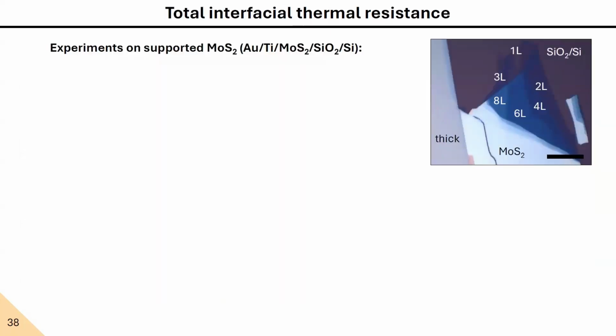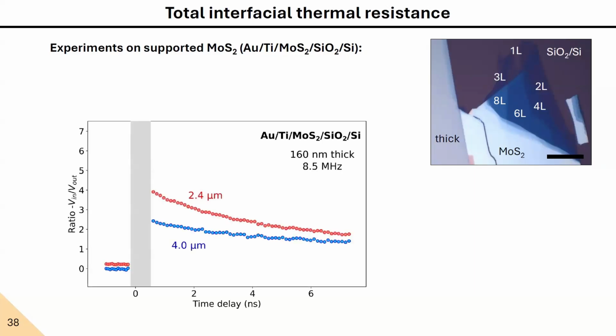So let's perform our time-domain thermoreflectance experiments on our thickness-controlled supported flakes. So for the thick regions of our flakes, these are 160 nanometer thick flakes, we have our pump laser introducing heat in the system and the heat decaying. If we use a smaller laser spot size, the temperature increases much more, and therefore it produces a larger signal.